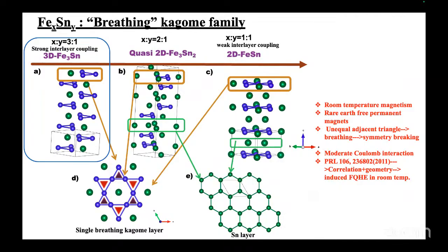Usually in the ideal Kagome, the triangles are equal, but in this class, the triangles are observed to be unequal, which further leads to an anisotropy. No, I understand that they are unequal. But what I'm saying is that you cannot just say that if one triangle is smaller than the other, the left one will always be smaller than the right one. It can be dynamic, and in that sense it really justifies this breathing mode, which I think should come from this type of distortion. I don't think so, it is random. It is quite adjacent.